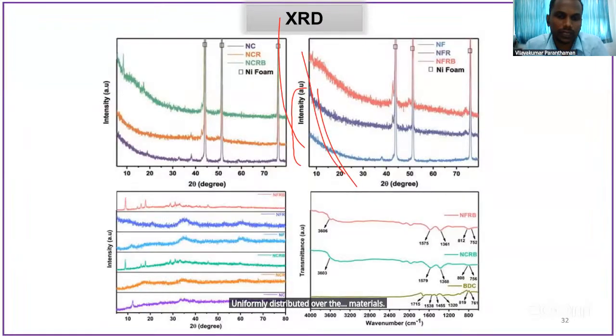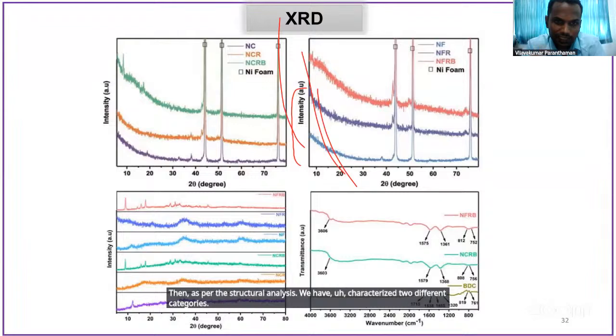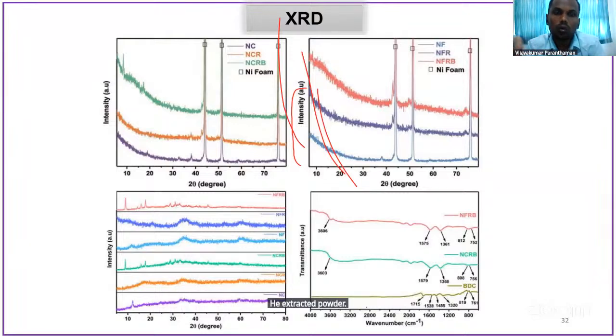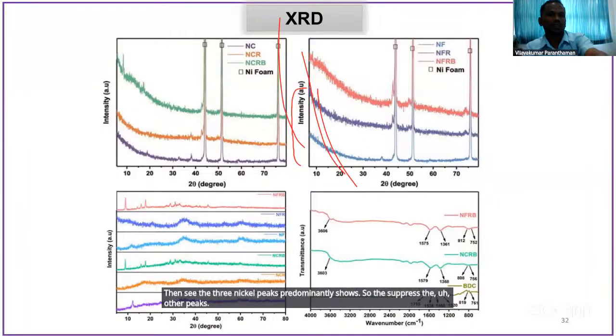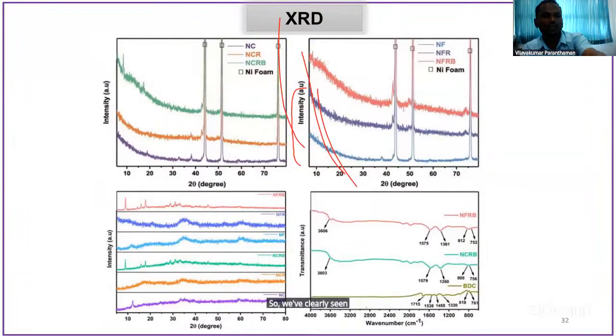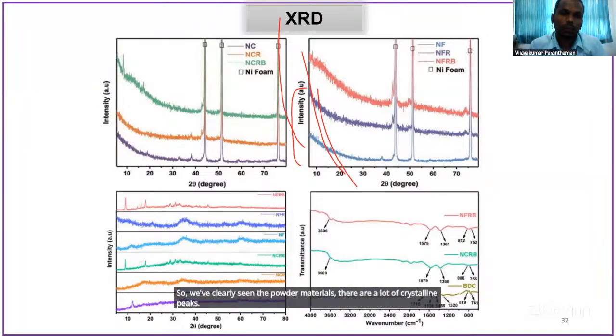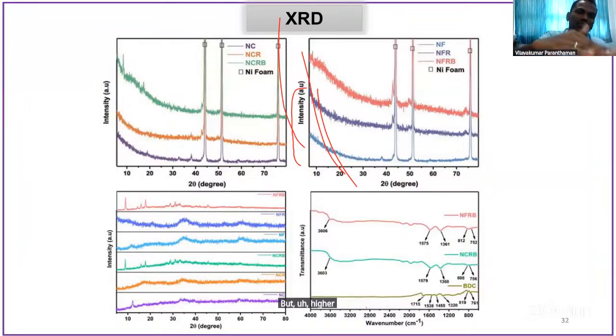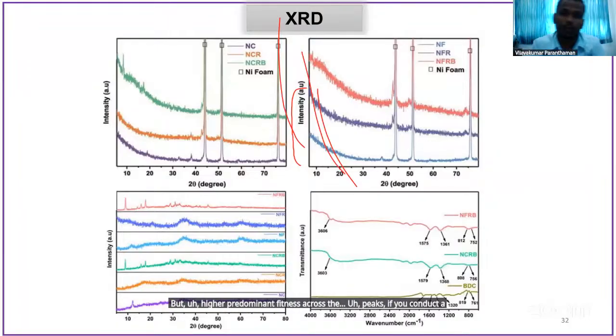Then for the structural analysis, we characterized two different categories: extracted powder, and the material over the nickel substrate. The three nickel peaks predominantly suppress the other peaks. So we clearly see in the powder material there are a lot of crystalline peaks, but the highly predominant nickel suppresses the peaks if you conduct the analysis on the nickel foam. So we confirmed the material structurally.